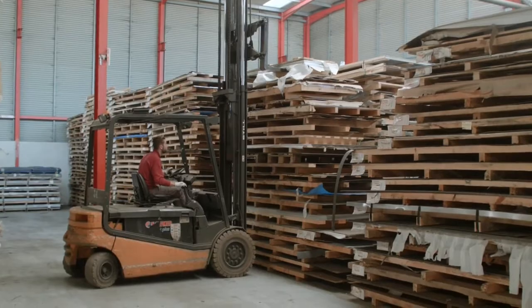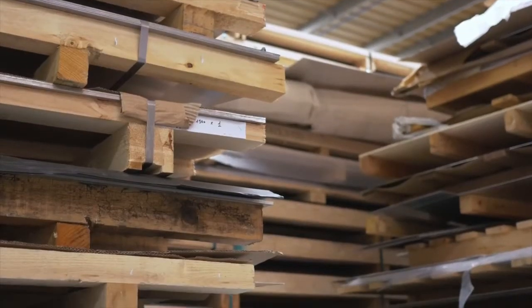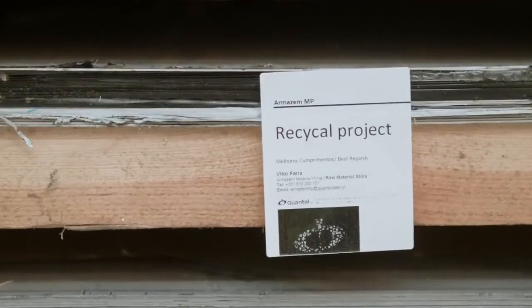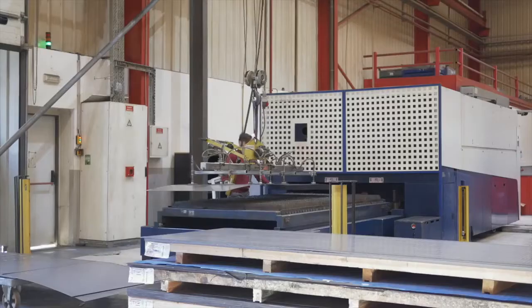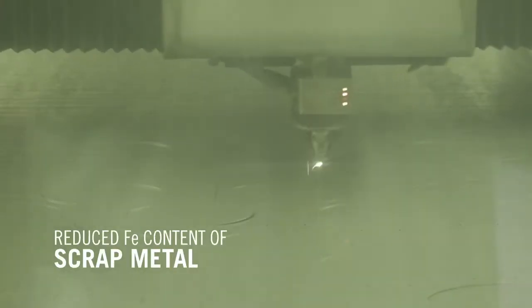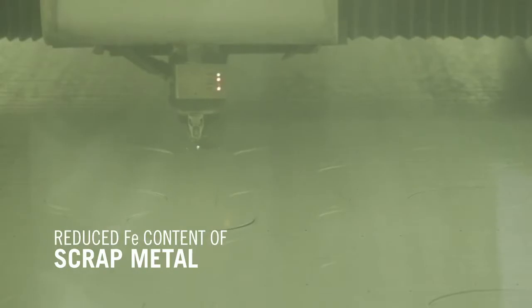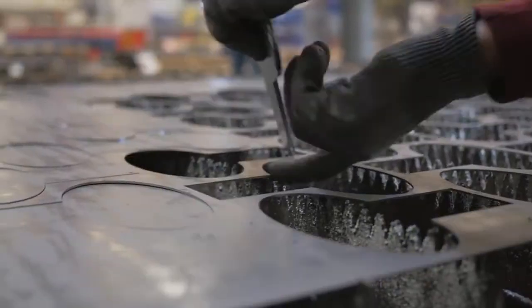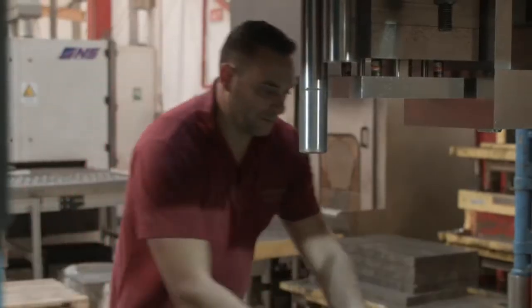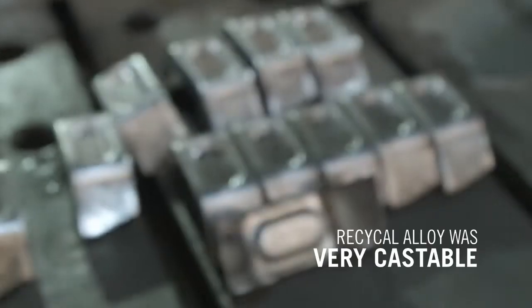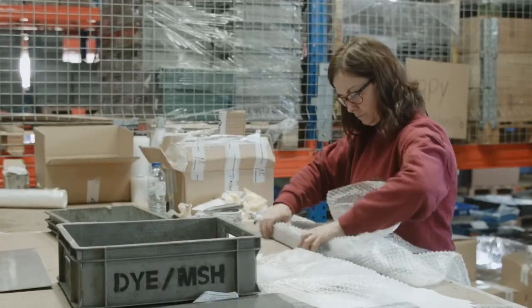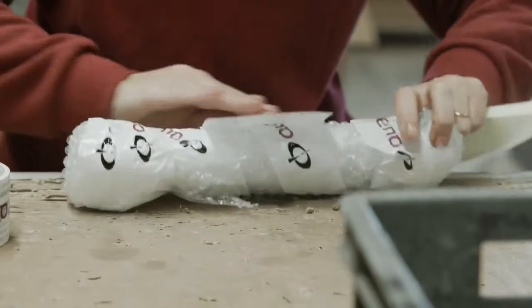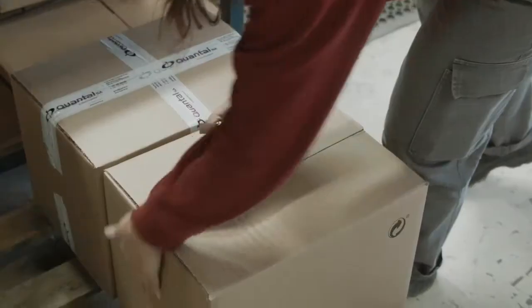A prototype component made using RecycAl material was cast and tested. The results showed the reduced Fe content of RecycAl material met the component specification, as did the tensile strength and hardness properties. The RecycAl alloy was very castable and did not need flux, grain refiners or melt degassing required by some other casting alloys currently used.